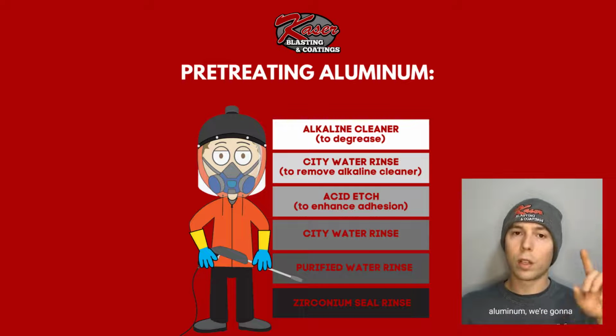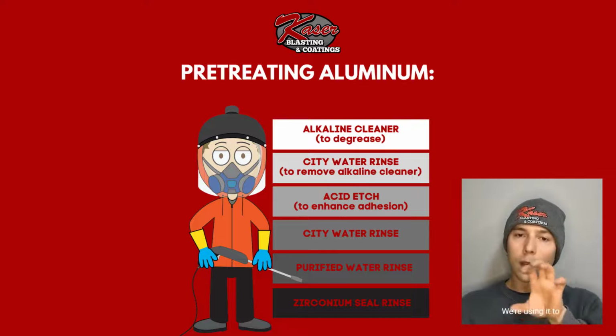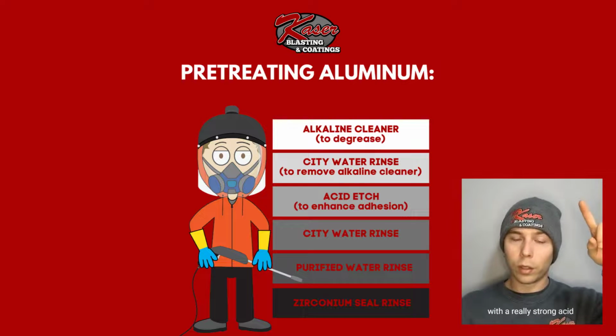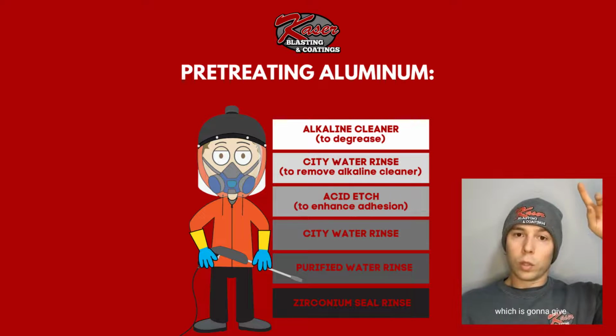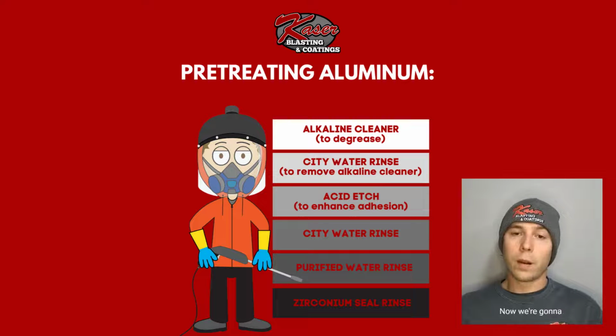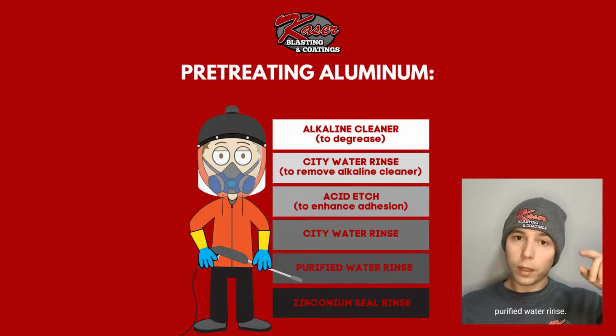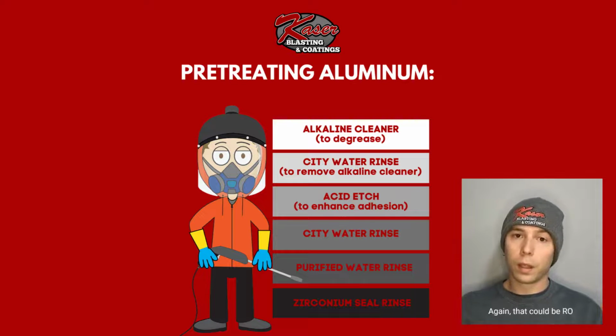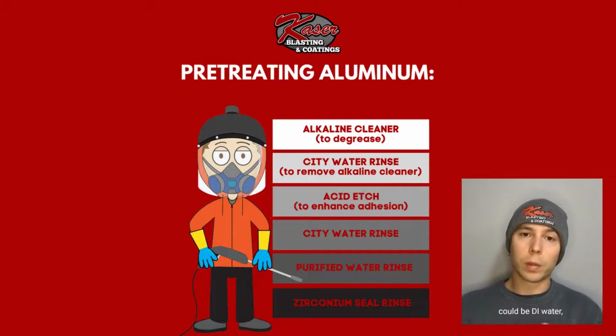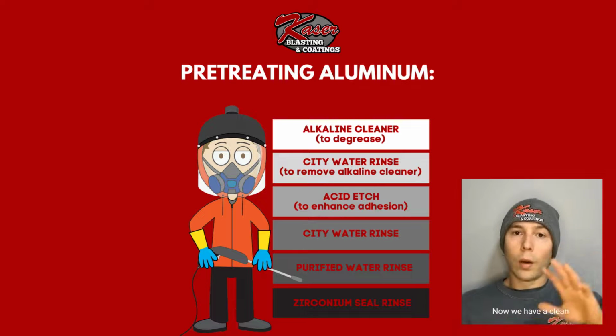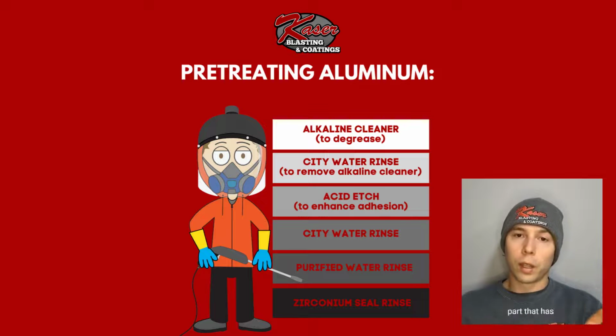So since we're on aluminum, we're going to use a strong acid, low pH. Lower the pH, stronger the acid. We're using it to etch the aluminum. We can get away with a really strong acid because the aluminum is not going to flash rust on us like steel would. So we've done some sort of acid etch, which is going to give us better adhesion to the aluminum. Now we're going to rinse that away. So we're doing a city water rinse again. And then we're doing some sort of purified water rinse. Again, that could be RO water, reverse osmosis, or DI water, deionized water. Now we have a clean etched aluminum part that has been rinsed clean.